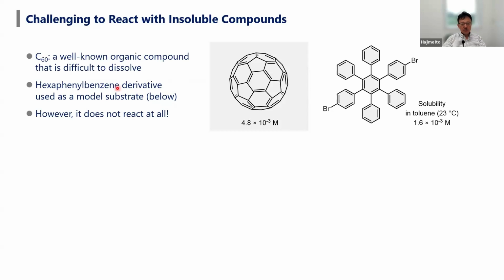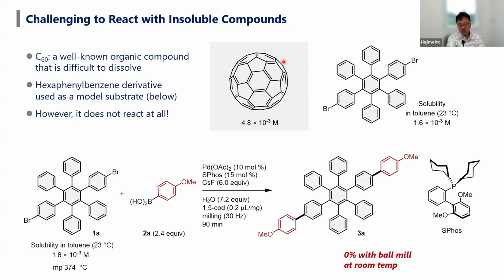So we first tried cross-coupling of these substrates because the solubility of this substrate is comparable to carbon-60. If we can conduct this cross-coupling, it would be a very good demonstration for cross-coupling reactions of insoluble materials using ball milling.